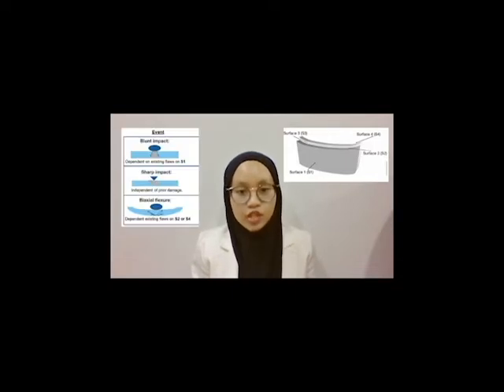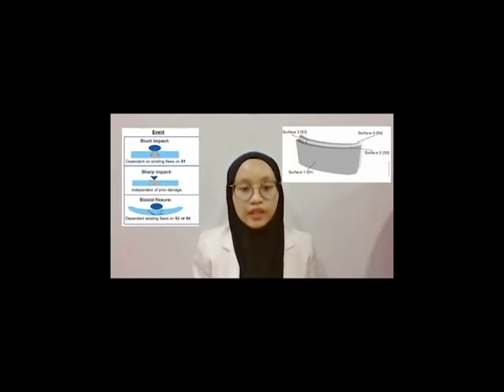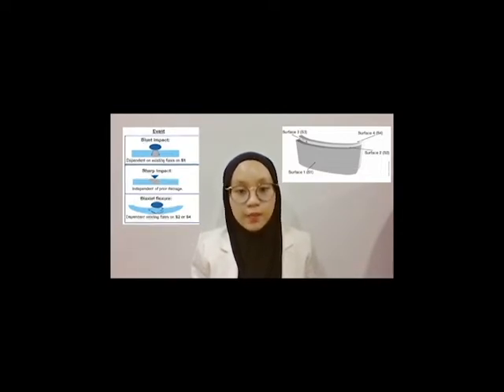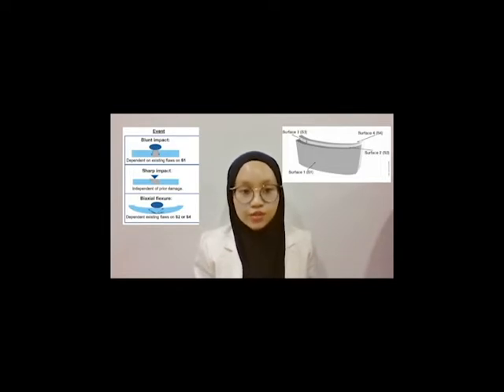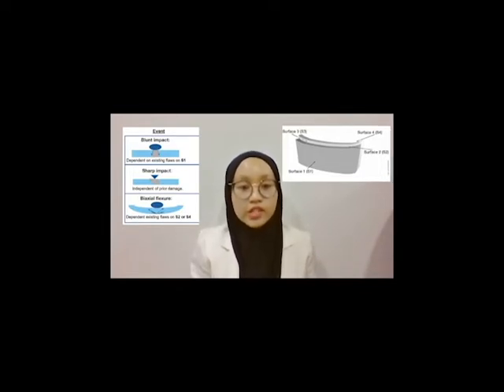The first one is the blunt impact. Hertzian contact stress causes radial stress on the outer surface 1 of the windshield and triggers an existing flaw. This results in a complete or partial ring crack that could turn into a cone crack. Radial cracks often occur when the cone crack exits the back of the outer ply at surface 2. Second is the sharp impact.